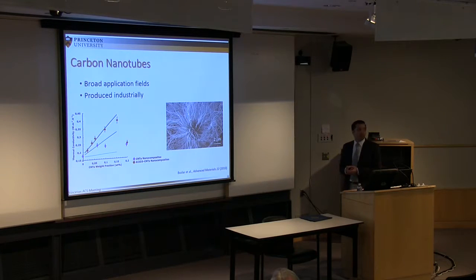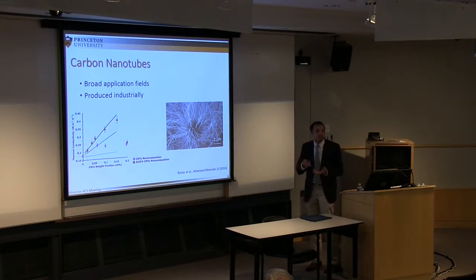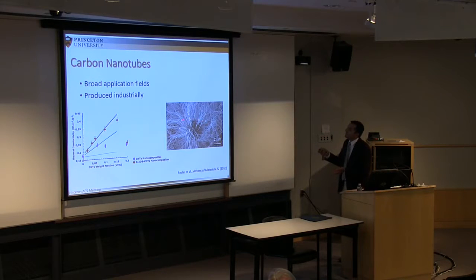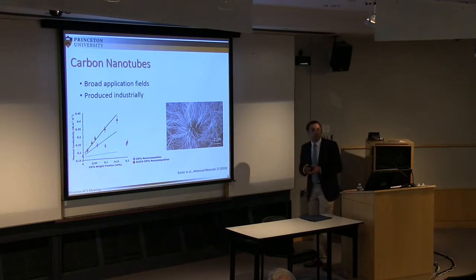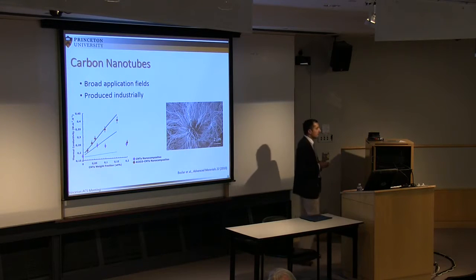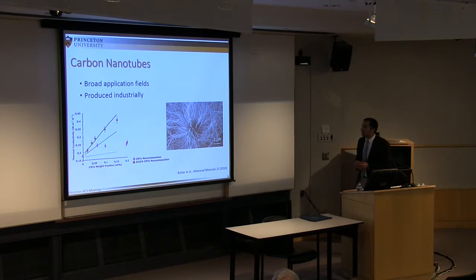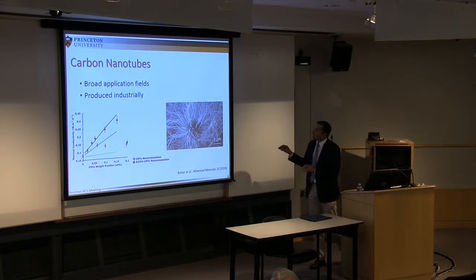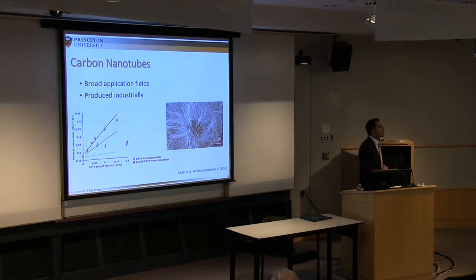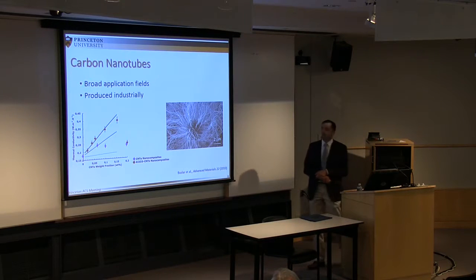And here's an example of application of the carbon nanotubes. You can grow them on ceramic substrate very easily. Because we knew that there was a dispersion issue, we took the ceramic particle alumina, in this case alpha phase alumina, micron size, and we grew the nanotubes on top of this particle. Why? This gave you a better way of controlling the dispersion of the tubes inside an epoxy matrix, for instance.